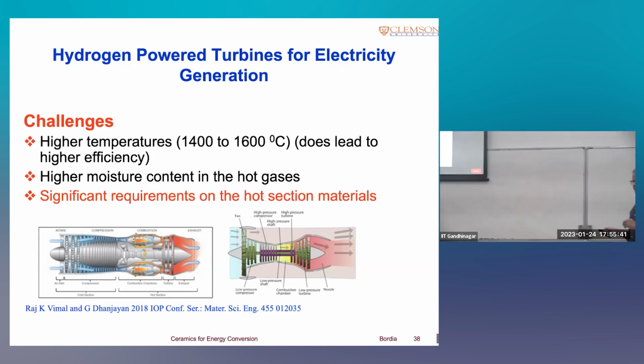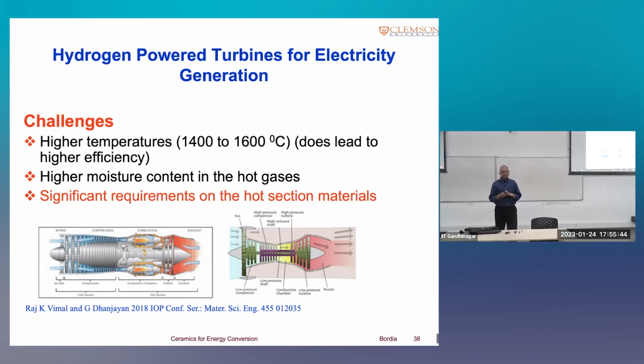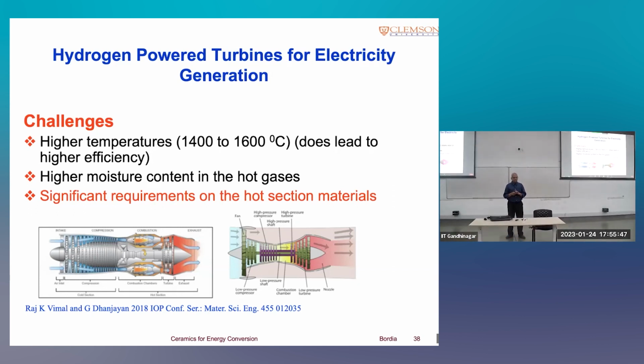There is a significant and growing interest in developing turbines that can burn hydrogen. So instead of natural gas, for example, people would like to burn hydrogen to generate power using turbines. And it turns out that there are challenges. The two biggest ones are that with hydrogen, you get much higher temperatures in the turbine. And the second thing is that because the only combustion product is water vapor, the partial pressure of steam is much higher in the turbine. And steam is very corrosive to metals, and the higher temperature means that most metals cannot be used.